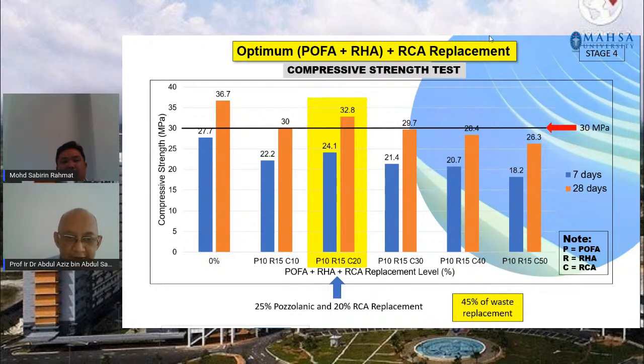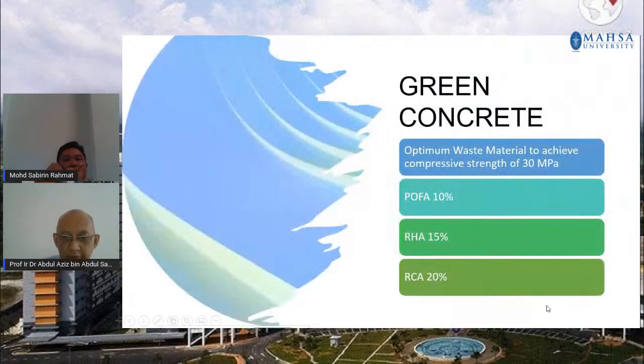So this is practically the percentage of waste material that we'll be using in our green concrete: 10% POFA, 15% rice-husk ash, and 20% recycled concrete aggregate. All right. Okay, so the green concrete, to achieve a compressive strength of 30 megapascal only, you must be aware that this study is only focusing on a strength of 30 megapascal. So the POFA is at 10%, the rice-husk ash is at 15%, and the recycled concrete aggregate at 20%.